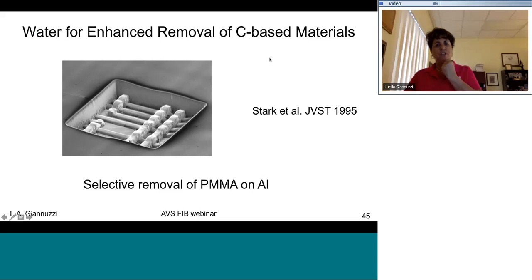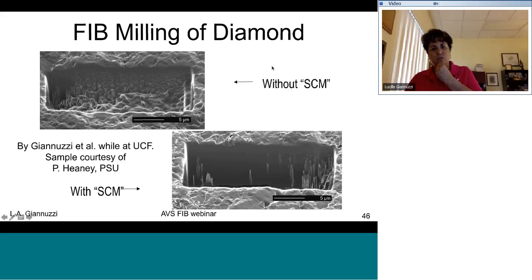You can also use enhanced etching for removal of certain materials over another material. This is called selective etch. For example, this is selective removal of PMMA on aluminum. So here we can selectively remove, for example, the PMMA leaving behind the aluminum structure. You could mill diamonds with selective carbon mill or water etch. This again helps to enhance the etching. So this is the same pattern with and without the water source, and you can see that you can go a lot deeper and get a lot better surfaces.